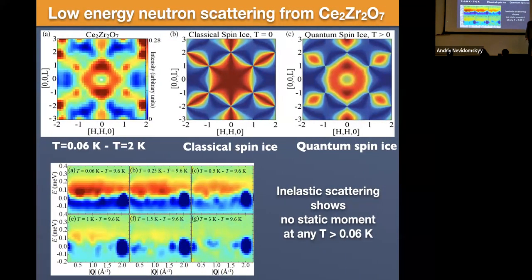Okay, so here I am, well into the presentation. I'm only now getting to the low energy physics, which is the part that most condensed matter physicists care about. And I'm showing you our low energy experiments now on cerium zirconate. And so now instead of doing spectroscopy at 500 meV or 150 meV, I'm doing spectroscopy below 1 meV. Okay. And I'm actually taking data, and I'm just looking at all the data as a function of energy and the modulus of Q. And these are measurements on a single crystal sample.